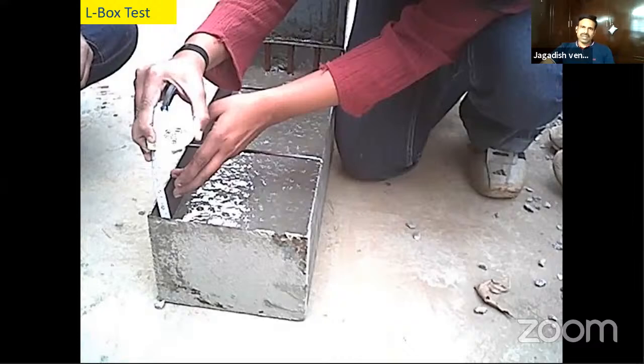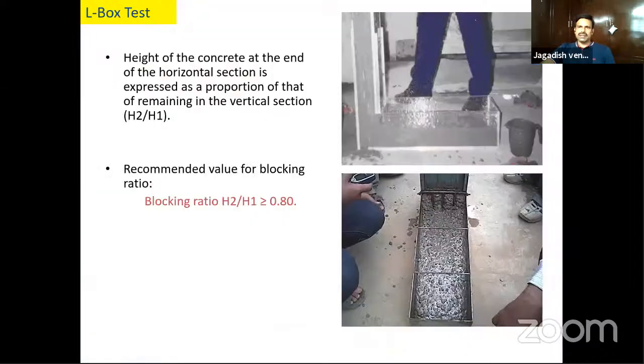So once you fill the concrete in the vertical box, you lift the gate. The concrete has to flow through this reinforcement, and you measure the heights in both ends. The ratio between both the heights will give you the blocking ratio. So it should be greater than or equal to 0.8. It should be more than 0.8. If it is less than 0.8 means, there is a problem with the mix.